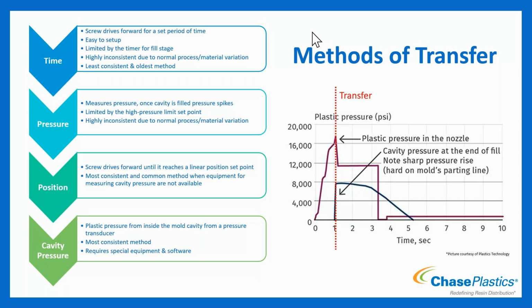If you have transducers in your cavity because you intend to do something like a decoupled 3 process, you can also use the signal from those transducers to transfer from fill to pack. You will typically have a transducer near the end of fill, and when the transducer starts picking up pressure, you know that the melt has reached that point in the cavity, and you can transfer over to pack from there. That allows you to transfer consistently at the same cavity pressure. That is also an extremely successful method for triggering transfer and offers a high degree of repeatability, but does require those transducers to be able to accomplish that method.